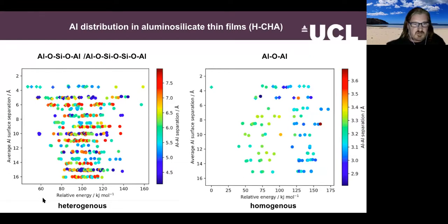But you can see here that we've got a relative energy plot. Now, it turns out that it's actually much more favorable to form aluminium, oxygen, aluminium linkages when you have protons present as a charge compensating species. And it's much less discriminating about where the aluminium is, except for one particular configuration. Now, this points towards competing things going on in the structure. It's recently been reported that actually the silicon within these materials is quite dynamic, and contrary to popular opinion, it can easily come out of and go back into the structure, and hence we expect the same thing to happen with aluminium. So there's a layer of complexity, if you pardon the pun, to do with how the aluminium is distributed within these thin films